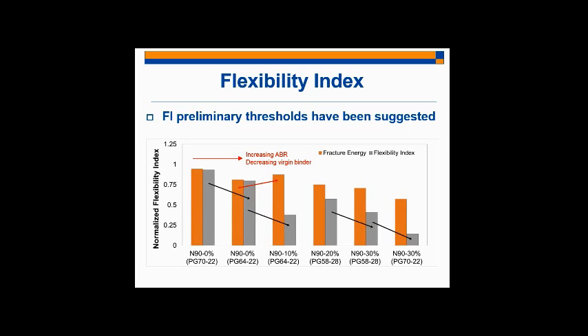Then as I further deteriorate the mixture and add an additional 10% asphalt binder replacement, resulting in a 30% total asphalt binder replacement value, I get a further decrease. And then finally, when I use the worst possible combination of all these parameters, so 30% ABR, 7% RAS, and then PG70 minus 22, I get a further decrease. So the flexibility index trends are intuitive, right? And they make sense. You would expect the two extremes of the spectrum to be which two mixes, right? You'd be expecting the N90 0% 70 minus 22 to be the best performer, and the N90 30 70 minus 22 to be the worst performer. And so this is a further validation of the flexibility index.